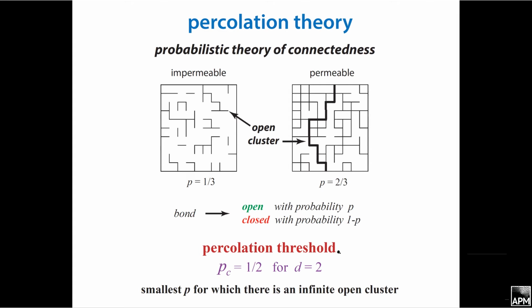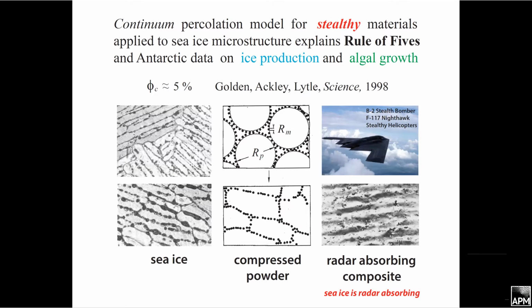But then the real question is, what is the percolation threshold, the smallest value of P for which there's an infinite open cluster? And for the two-dimensional square lattice, it's known that it's exactly 1/2 or 50%. So why in the world are we down so far at 5% for sea ice? And it turns out that there's an excluded volume effect, that the brine inclusions, the fluid phase in sea ice, are not just randomly distributed, they live on the boundaries between the individual crystals.